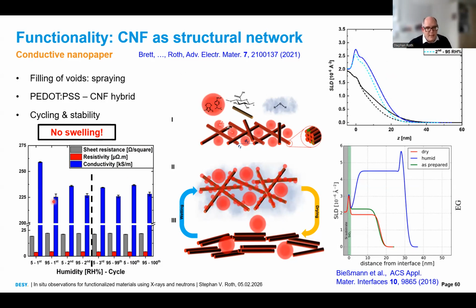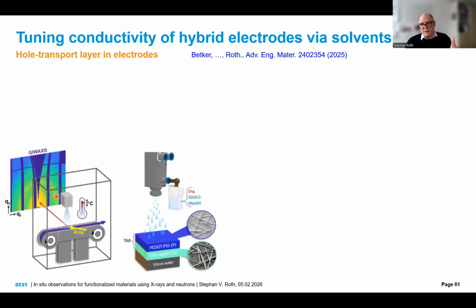You see here, important is, when we go out here, we always have humidity. But the humidity changes, of course, the conductivity, but we can do this 100 times. We can dry it and humidify it, and the structure changes in a cyclic way and does this in a stable way. And this is very important, what we got to know from here.